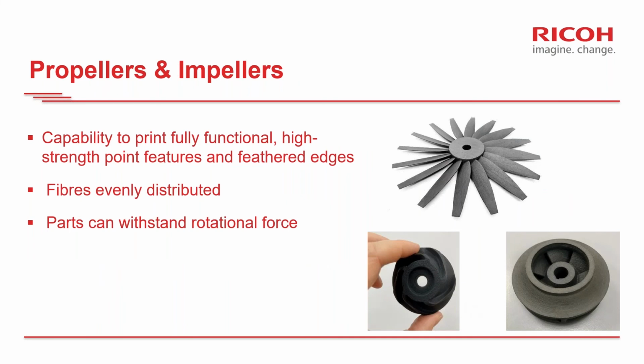Another very successful application for the CBAM technology is the production of functional propellers and impellers. In this case, thanks to the fact that you have an evenly distributed fiber content throughout the part, you are able to produce fully functional, high-strength pointed features and feathered edges that can actually withstand the rotational forces without breaking. Some of the customers we have been working with have tested propellers and impellers made with the CBAM technology, and they've realized those parts can achieve a performance comparable to those produced by injection molded glass fiber reinforced PEEK.